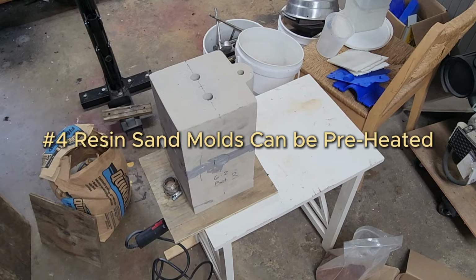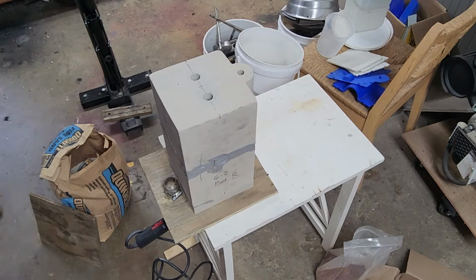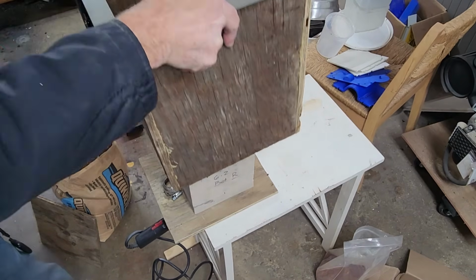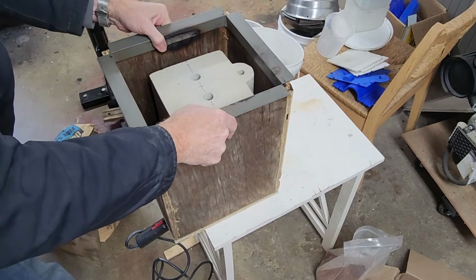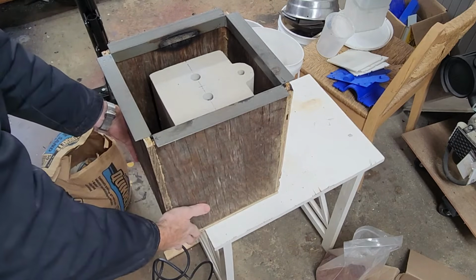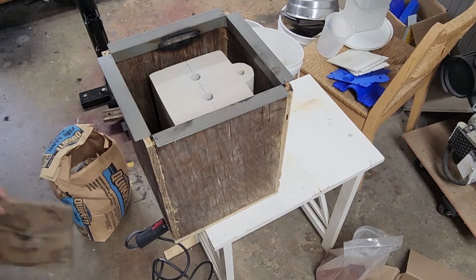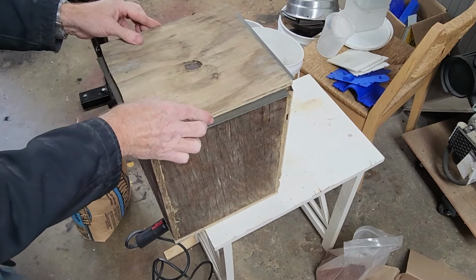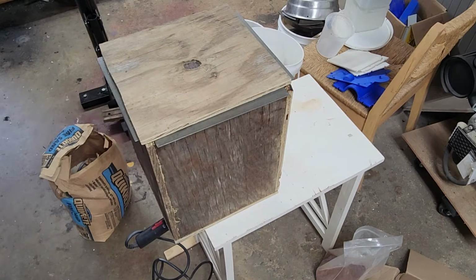With Petrobond, preheating the mold degrades the oil binder and increases gas defects. Resin-bonded sand, by contrast, can be safely pre-warmed up to 250 degrees Fahrenheit to stabilize the pour, reduce thermal shock, and dramatically improve surface quality, especially on thin sections.